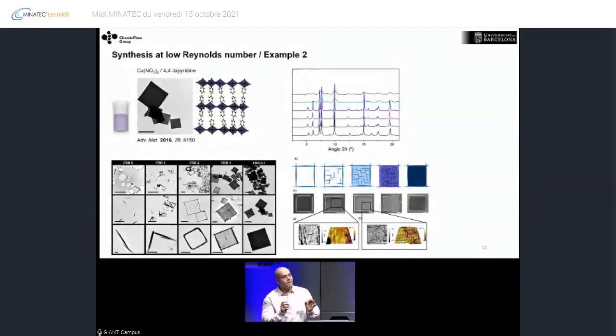So what this controlled reaction in microfluidics allows us, because we can control the diffusion of these two regions in time and space, is that we are capable of freezing the crystallization process. So we can isolate states that are intermediate states towards the final thermodynamic product that is this one here.